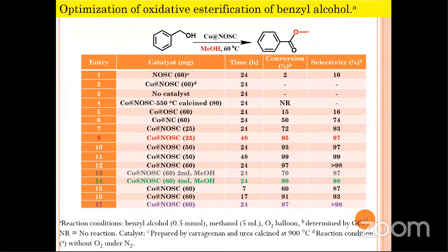Based on the properties, I have chosen the esterification reaction. In literature, I found that cobalt was used for the esterification reaction, but they used a base like NaOH with the cobalt-based material. But here, I did not use any base. The nitrogen, oxygen, and sulfur act as the activating agent for this reaction. You know that pyridinic nitrogen can act as a base. So base-free oxidative esterification was achieved by using this material.